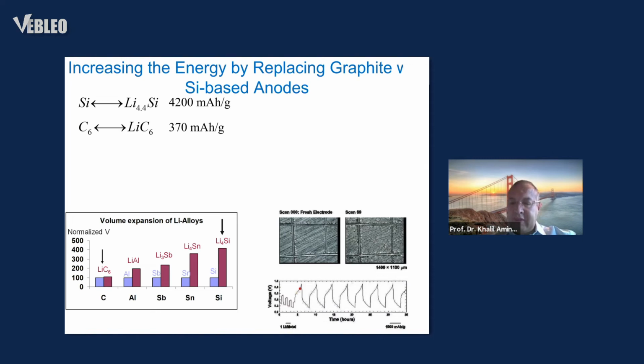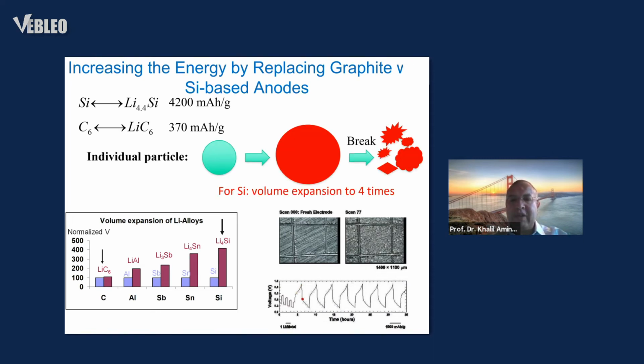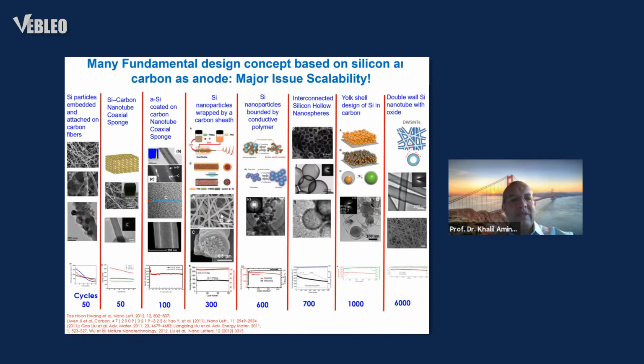So the problem is that you create cracking, and at the end, you have a pulverization of the particle and isolation, and then you have a significant capacity fade. So we need to address this. And a tremendous amount of work has been done on trying to incorporate silicon inside different carbon matrix, as you can see here, or basically designing conductive binders that can incorporate the silicon when it pulverized, for instance. And they've shown some decent result. The only concern here is that the loading is very small. So you have a shallow charge and discharge.